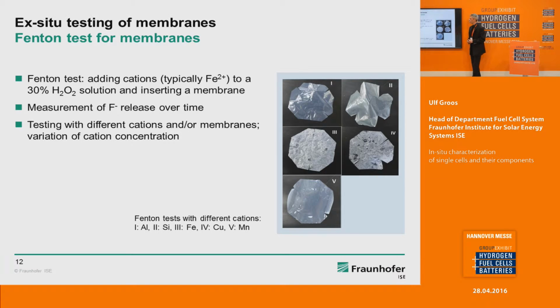Secondly, we look at ex-situ testing, and this special method is called Fenton tests. So we investigate the contamination effects of different cations. It might be iron, which is especially harmful, or copper, or aluminum, or other cations. Here you see some results after doing this Fenton test with different cations. So we can investigate the chemical stability of different membranes.